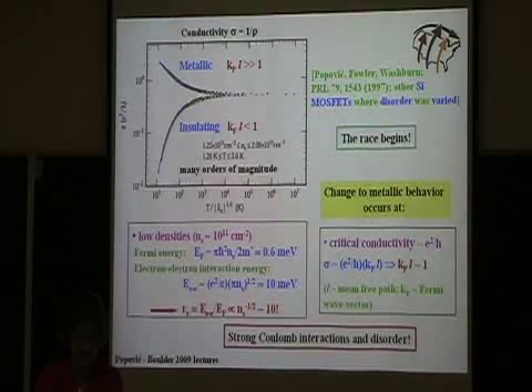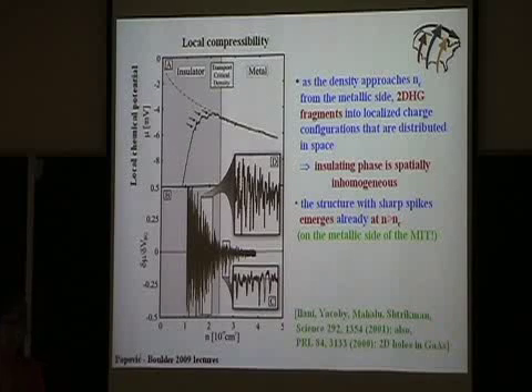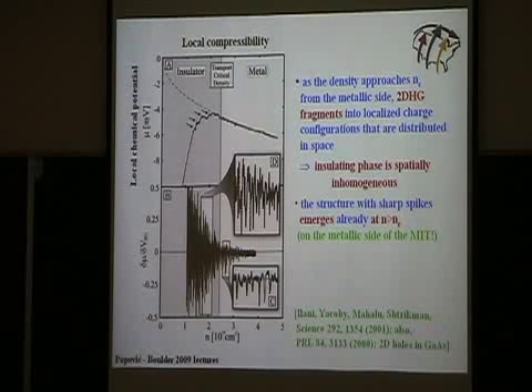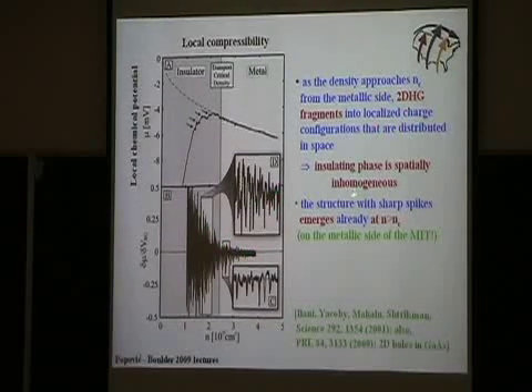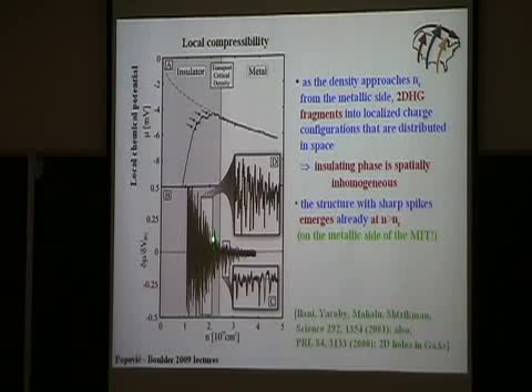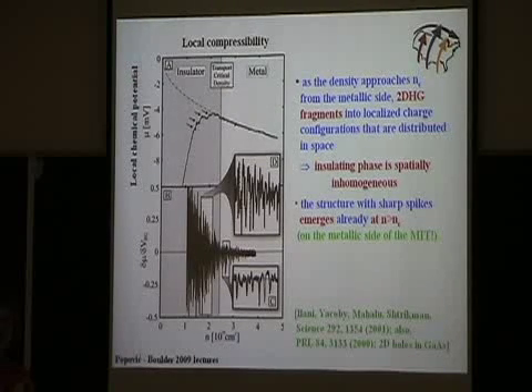And I'm getting close to the end. One other experiment I wanted to mention before I talk about glassiness tomorrow is actually a local measurement of the charge distribution in a 2D system. These were 2D holes in gallium arsenide. And they found that as they reduce the density, approach the insulating state, they start seeing the development of inhomogeneities in the charge configuration, spatial inhomogeneities. And the onset of this actually takes place before one gets to that separatrix. So this is, again, I think relevant because it also shows these inhomogeneities. It's kind of similar to those STM studies.